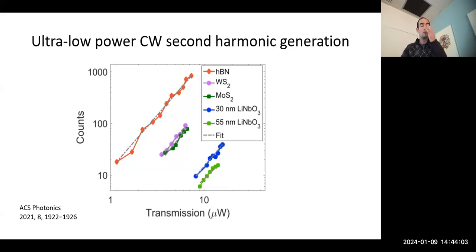So just looking at the transmission of light through the aperture for different materials, tungsten disulfide, molybdenum disulfide, and HBN, we see the expected power dependence on the emission, but we also observe that the HBN, tungsten disulfide, and molybdenum disulfide have a lot more harmonic generation, so second harmonic generation, than even a nonlinear optical crystal.